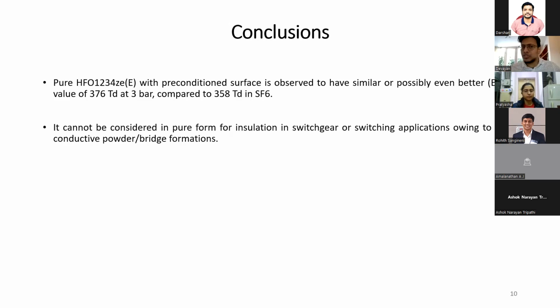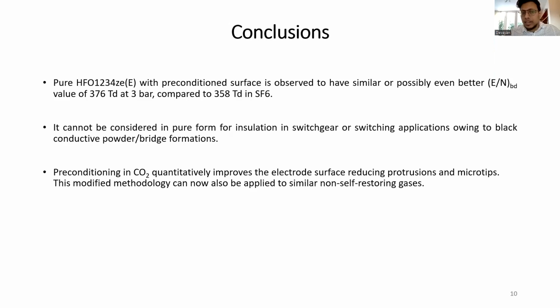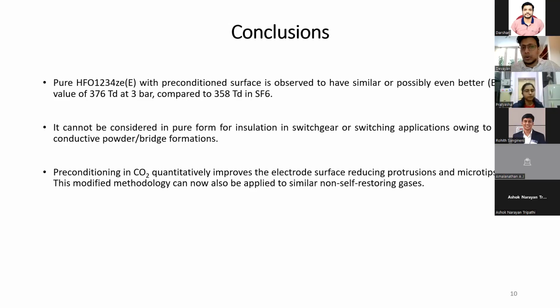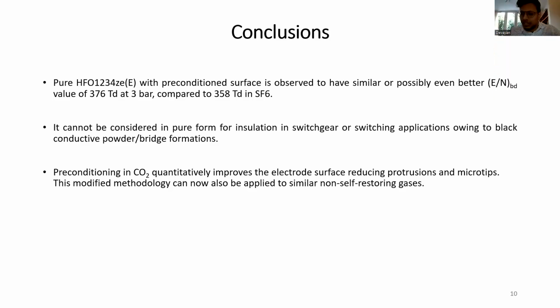Why? Again, because you saw there was this black conductive powder and the bridge formations. And thirdly, preconditioning CO2 that we saw quantitatively improves the electrode surface, and it also reduces the microtips and the protrusions. And this modified methodology can now be applied to similar non-self-restoring gases as well. So now you see what is non-self-restoring. It's more like once you start with the gas and you have breakdowns, you start depositing carbon, and then the E by N value also reduces subsequently. So that means it cannot restore itself to the best of the insulation conditions. And hence, it's a non-self-restoring gas.